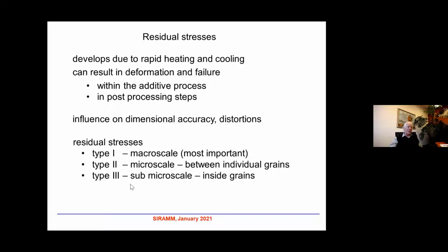And type 3 are sub-microscale stresses inside grains, and they influence the movement of dislocations. And finally, they can influence, for example, the behavior of the plastic zone in the case of fatigue cracks when they propagate very slowly. So all these three types of residual stresses can influence the fatigue behavior of materials.